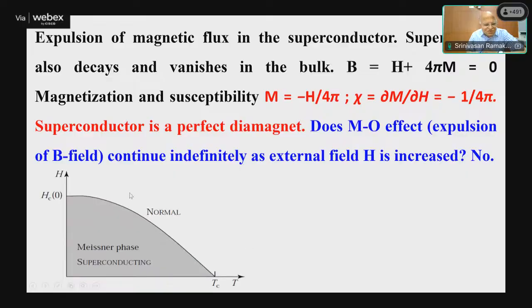So this was really a breakthrough in understanding superconductivity. You know how to understand the Meissner effect, how it expels the magnetic field. The expulsion of magnetic flux and the supercurrent also decays, vanishes in the bulk, and the magnetization also changes as a function of Tc. When you apply a magnetic field, you will see that the critical field, which was at 0 Kelvin, decreases as a function of temperature. This was also done from thermodynamic analysis, which we'll see. So the critical field, that is, you apply a field to a superconductor, its Hc decreases, and it decreases in this fashion. It's a parabola.